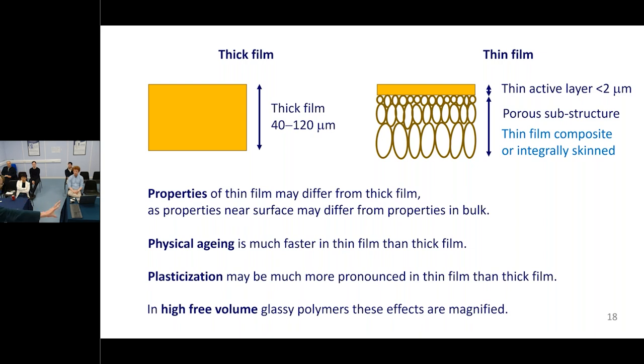So we're trying to get high permeability, which means we're talking about polymers which have a lot of extra volume, what we call free volume, high free volume polymers. And all of these things are much more significant in high free volume polymers, since there's a lot more space and a lot more potential to lose it. So in terms of current research, we're very interested in what happens as we move from thick film to thin film and how we control some of these effects that occur when we're dealing with very thin films in a composite, for example.